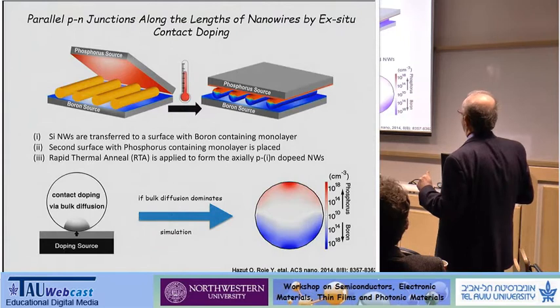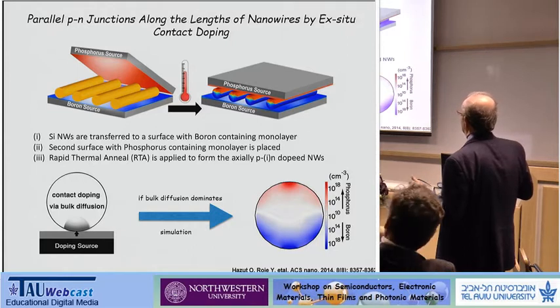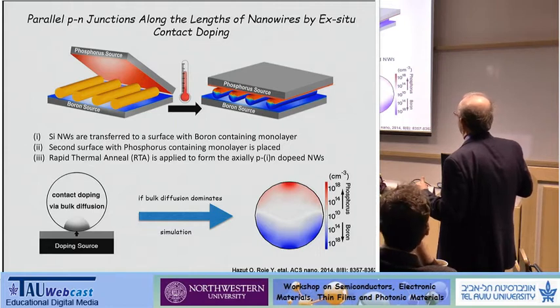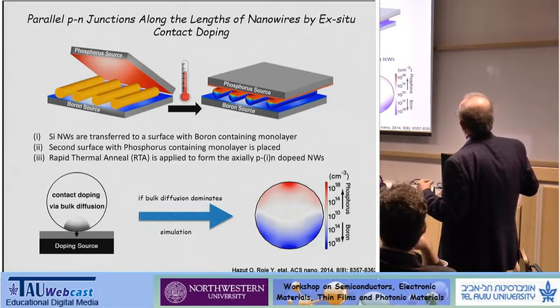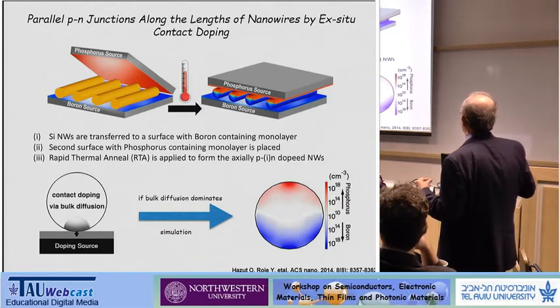Okay, so this is just a schematic of what's done. The silicon nanowires are horizontally sitting on, say, this substrate. So this is a substrate. It's the source of boron. So it's silicon, and it's doped with boron to the level of 1 monolayer. And then on top of the silicon nanowires, which are sitting here horizontally in parallel, you have the phosphorus source, and then you form this sandwich with the silicon nanowires in between. And the objective is then to create PN junctions along the whole length of these silicon nanowires.